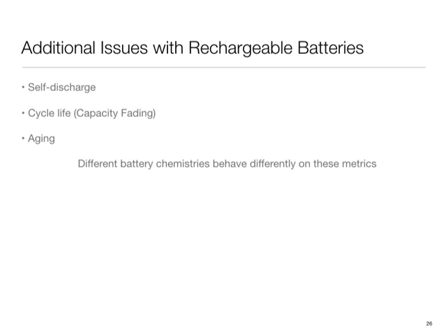And then finally, aging, which is kind of related to that. The difference is the following. Cycle life means that if today I bought the battery and I cycled it 1,000 times, and if the cycle life was 1,000 cycles, then the battery capacity would have faded. Aging refers to the fact that I buy a battery and I do nothing with it. It just sits there. I'm not charging or discharging. It would leak away, and then if I decided a year later to use it, its capacity would have degraded. That is because of the degradation in the chemistry of the battery that will happen.